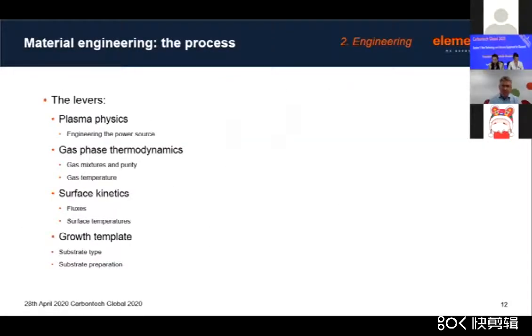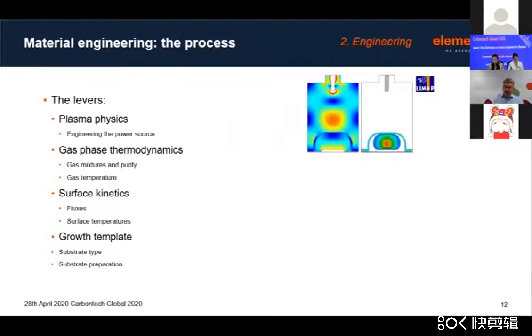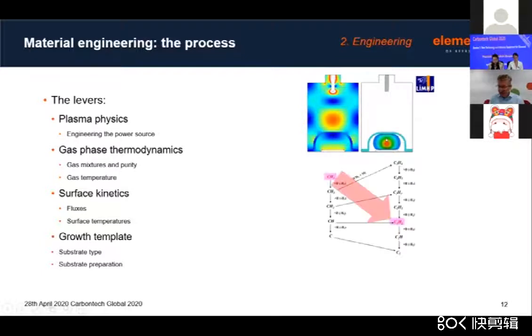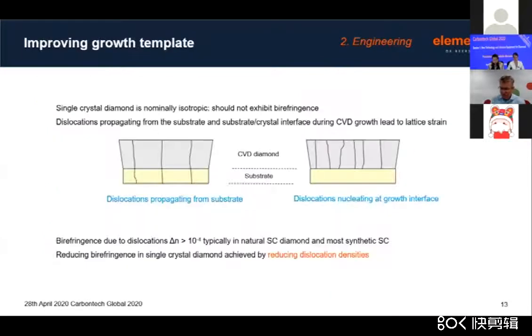The CVD process, though, unlike HPHT, gives you many more levers with which you can manipulate the properties of the diamond. We're able to model the plasma and the gas phase of that plasma to optimize it to couple in as efficiently as possible, and engineer the growth species and the temperatures of the gas phase. You can then look at the chemistries of the gases that you put in and try to optimize those to give you the best quality of growth or the highest purity or the fastest growth rates that you're looking to achieve. And you can definitely engineer an awful lot in the chemistry. And then finally, as mentioned, you can look at the substrates and the surface conditions that you get on your plasma, as well as the growth conditions, and manipulate that to optimize the growth process. So unlike HPHT, where there are limited ways of controlling the growth process, in CVD you can see many more and get more.